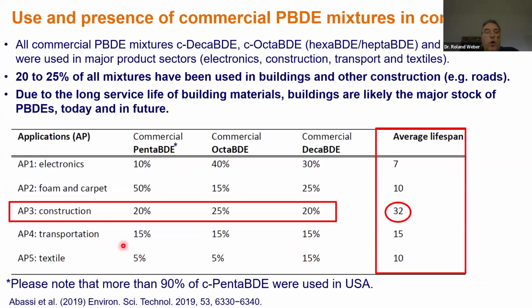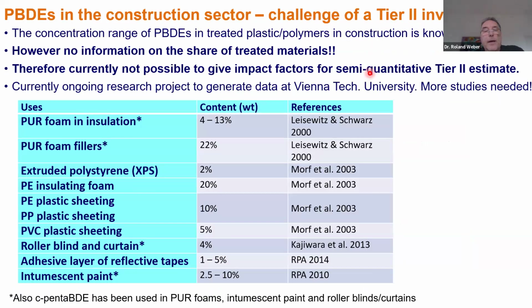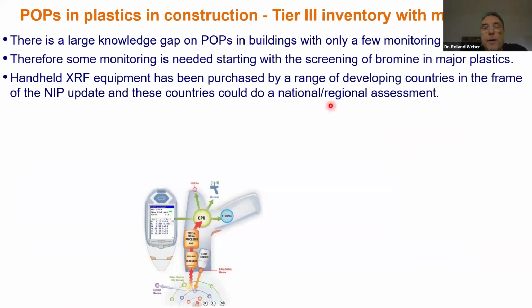For PBDEs, when we look into the overall use, we see that PBDEs have also been used in construction. For example, for DecaBDE, it is estimated that around 20% has gone into construction with a long service life. Also today, construction might be the largest sector for PBDEs. There are data on how much PBDE is included if polyurethane foam is used in insulation. But unfortunately, we do not have data on the share of treated materials. I don't know what percentage of the polyurethane foam has been treated with PBDEs. We have a study at the Technical University in Vienna where they are doing some measurements. But at the moment, PBDEs are really a black box and a big knowledge gap.